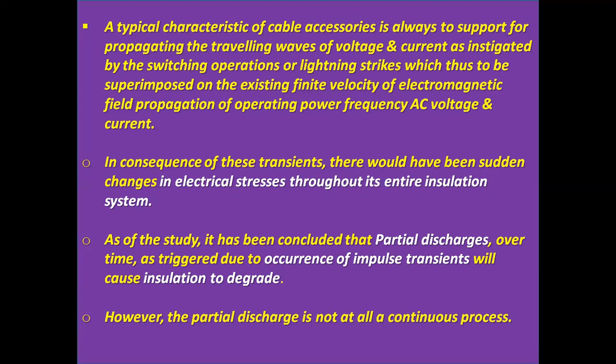As of the study, it has been concluded that partial discharges over time, as triggered due to occurrence of impulse transients, will cause insulation to degrade.